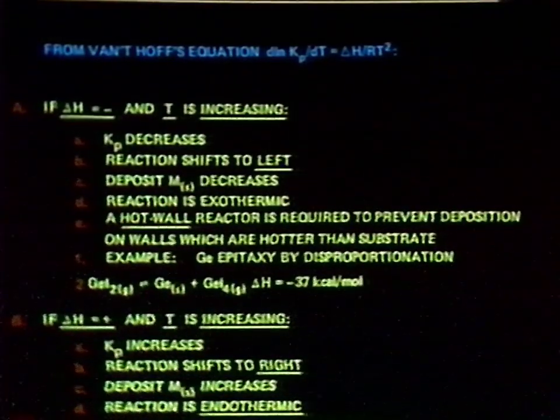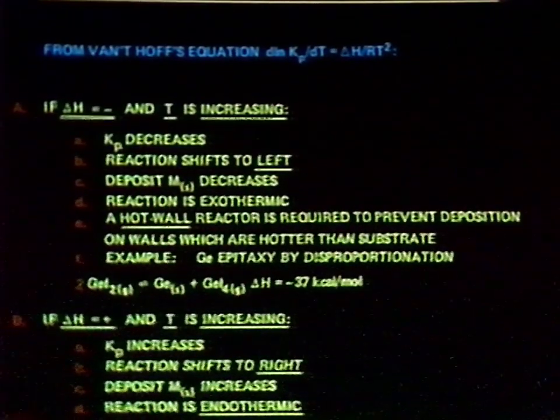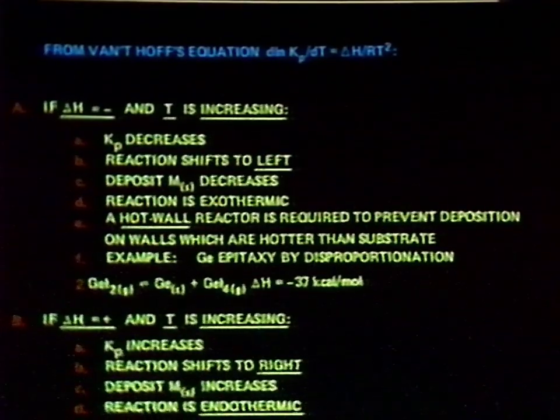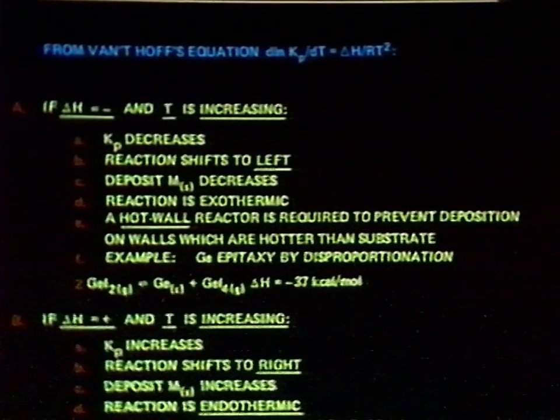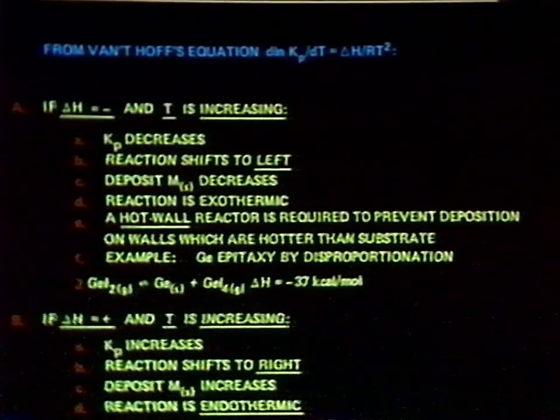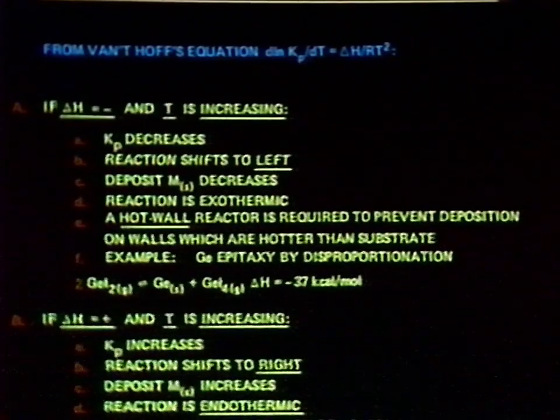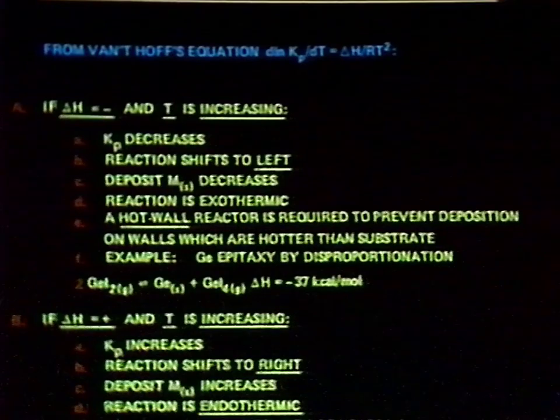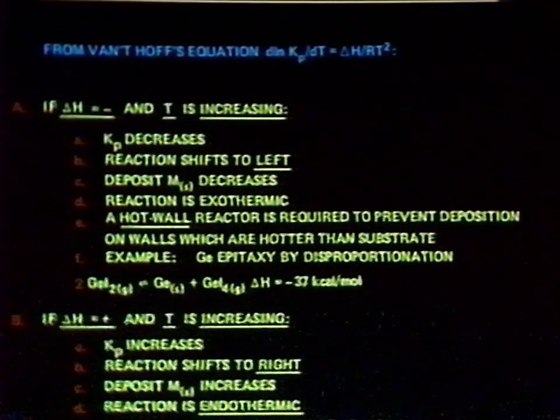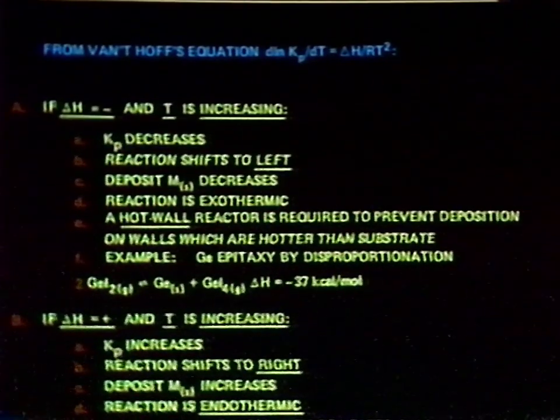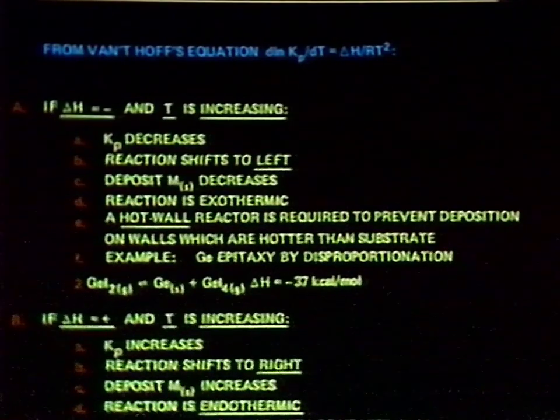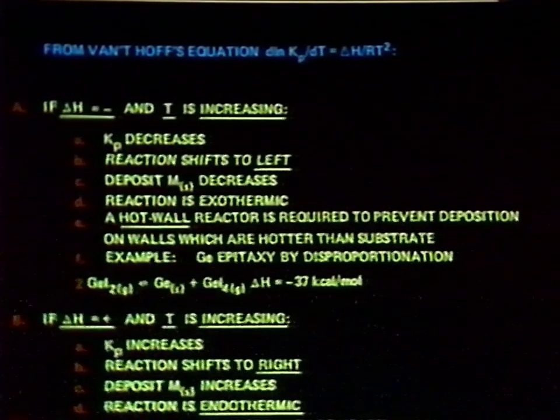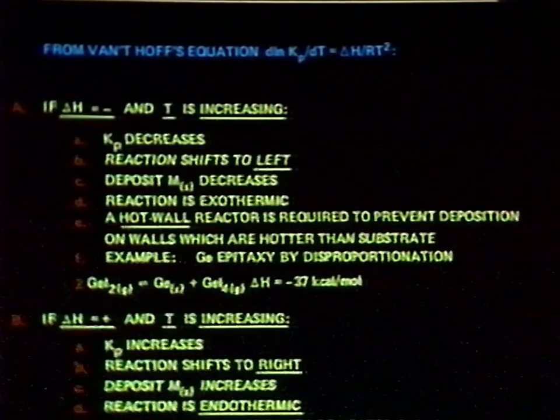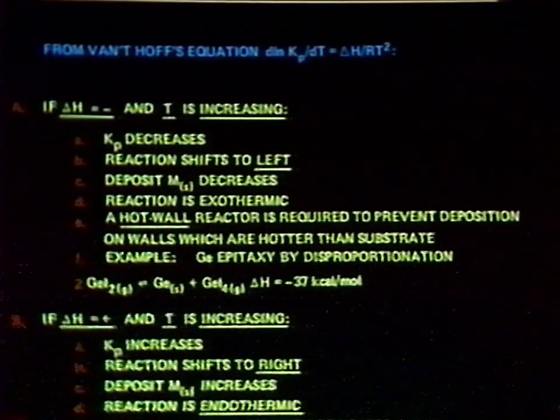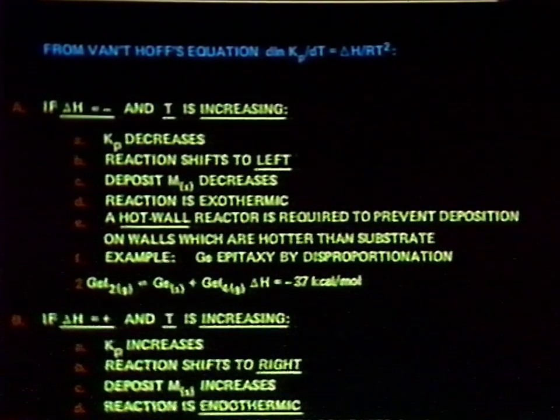Now let's look at a specific example, a very simple example of how we can utilize the type of calculations I have just shown. This will be for the selection of a reactor type using the Van 't Hoff equation we had just discussed. In this case, let's look at A here, where we start by saying that the delta H is negative and the absolute temperature is increasing. Then the sequence of events listed on the A, B, C, and so on takes place. The K sub P decreases, the reaction shifts to the left of the equation, the deposit M sub S decreases, and the reaction would be considered exothermic.